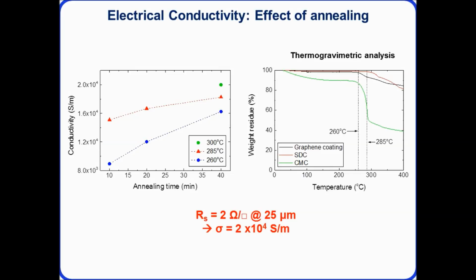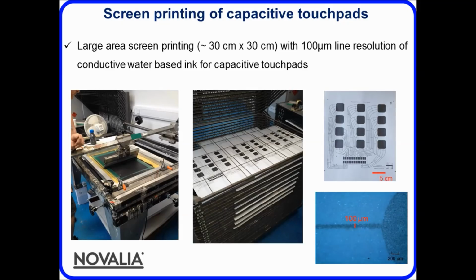Okay, so those are now giving us performance of 2 ohms per square at 25 microns. So those are the best films achieved to date. So looking at large-scale printing, we work with local companies in Cambridge. One of them in particular is called Novalia. So they're a university spin-out, and they develop their own conductive circuits for capacitive touch posters.